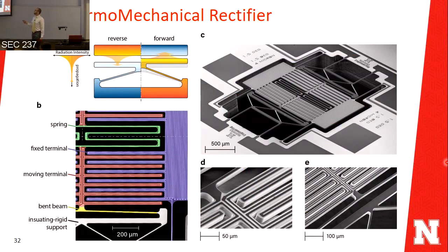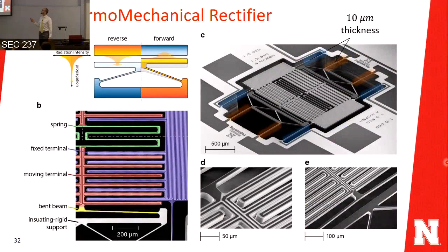So in the isometric view here, the device is completely suspended in vacuum through those supports. Each support is just 10 micron thickness, and the device is symmetric about the X and Y axes to increase the rigidity of the device and decrease the losses. The device has these main components. The blue shaded area is the fixed terminal. The red one is the moving terminal, and this is the bent beam, the actuator mechanism. And you have a spring here to give the moving terminal the freedom to move in plane. We have two platinum heaters, printed on the fixed and moving terminals to control both temperatures and measure the heat transfer.